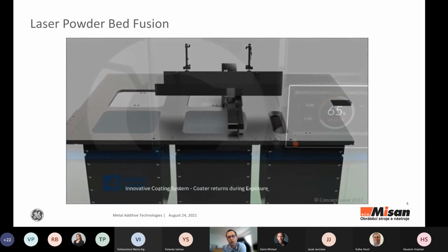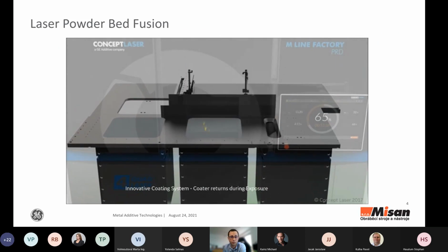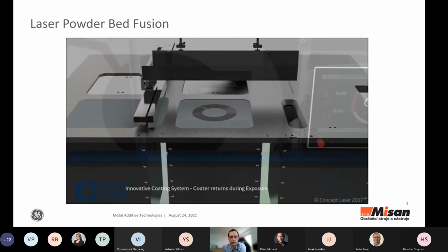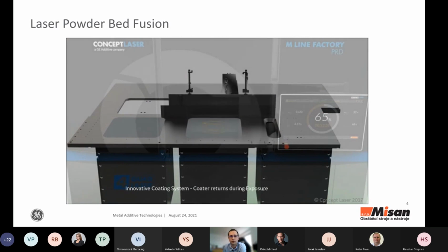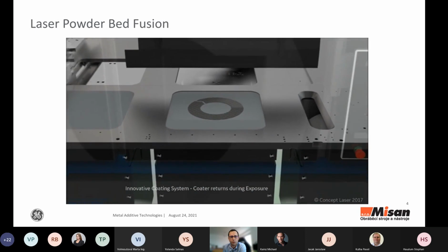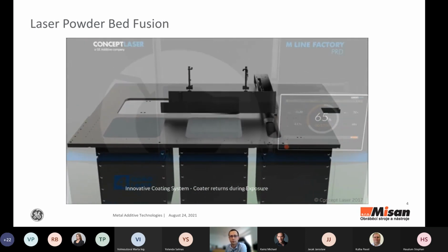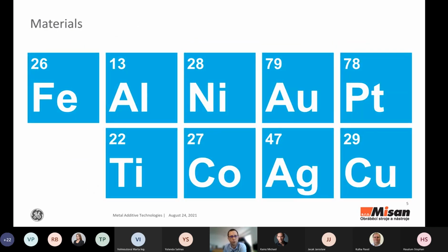So laser powder bed fusion, you may also know as SLM or DMLS. It's the most well-known technology, where you apply a thin layer of metal powder that you then melt with a laser, and then you apply another layer and melt it on top of the previous one. So this is basically the principle of this technology. We can build parts from stainless steel, aluminum, Inconel, cobalt chromium, also some precious metals, but one of the most frequent applications is titanium. It can be either Ti-6Al-4V, or commercially pure titanium, as well as some dental certified titanium.